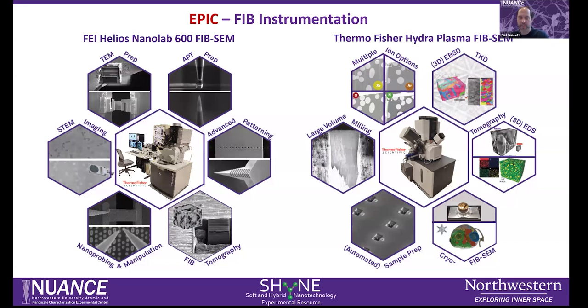Perhaps the largest hallmark of a plasma focus ion beam is that you can site-specifically remove large volumes of material, ranging from hard to soft materials, at very large length scales, typically up to the sub-millimeter range. An example is shown here on the left, a cross section of an alloy. Typically we would mill a cross section or surface, and the depth of this cross section is about 300 micrometers, achieved in about 5 minutes, giving you an idea of the high throughput volume milling possible with this instrumentation.